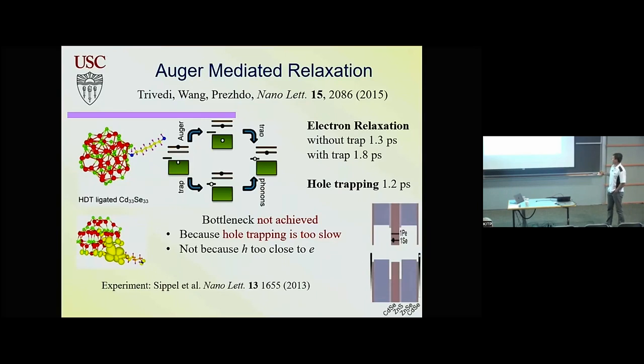But if your hole is coupled to your electron, because the hole has many, many states, the energy goes to the hole, and then the hole relaxes by vibrational relaxation, and then you don't see the bottleneck and you lose energy to heat, and this limits the efficiencies of many devices like solar cells and lasers.